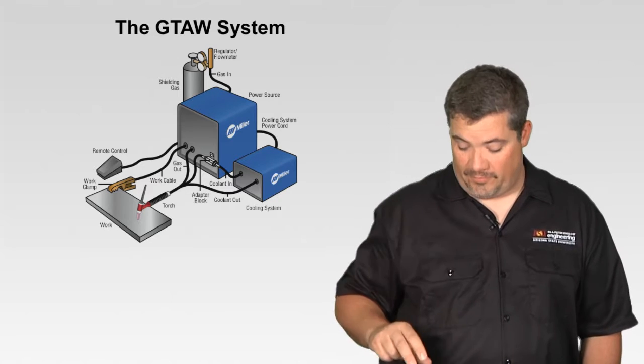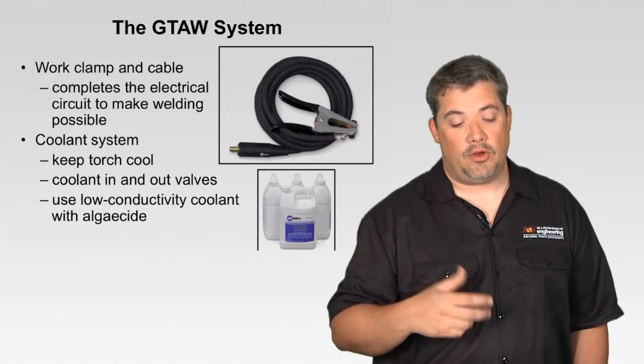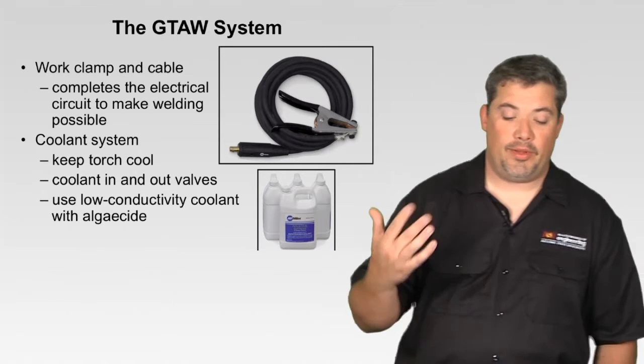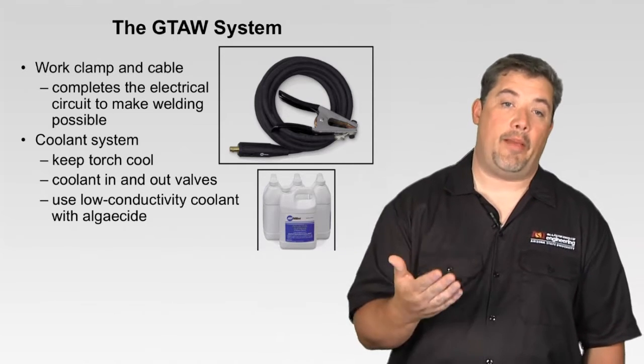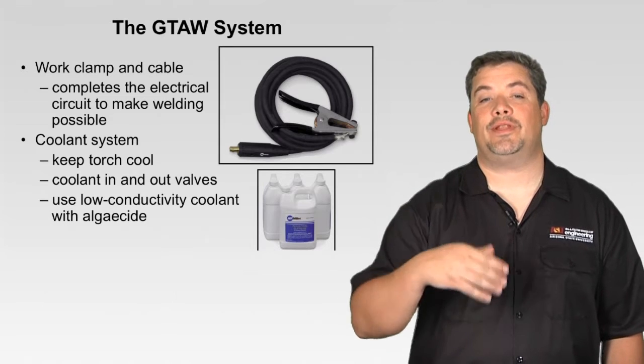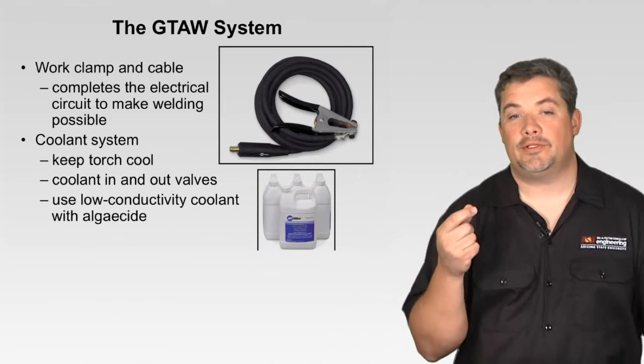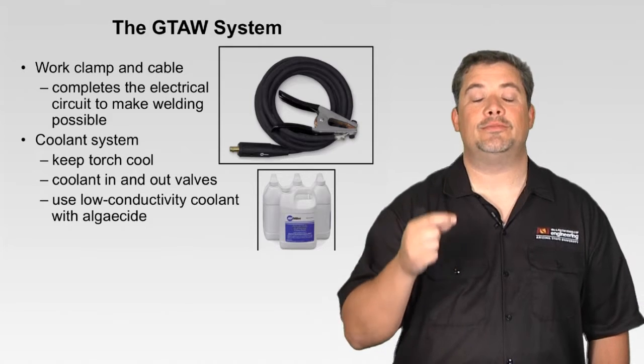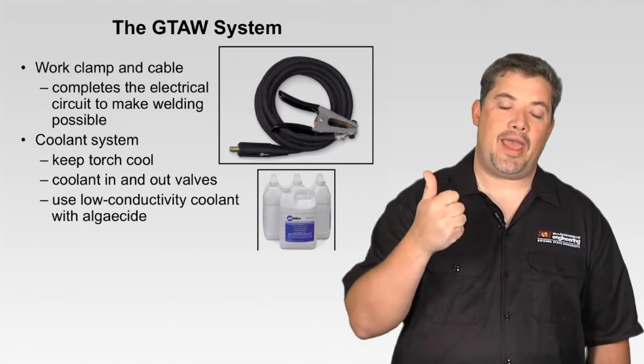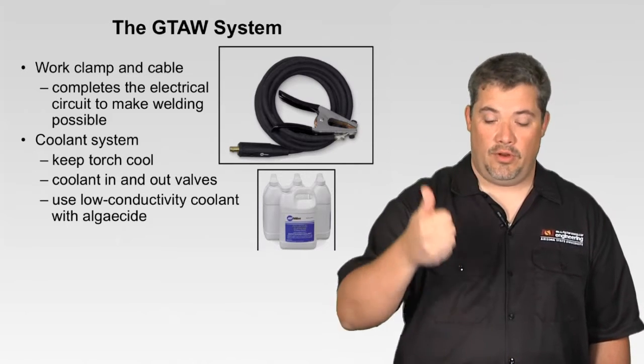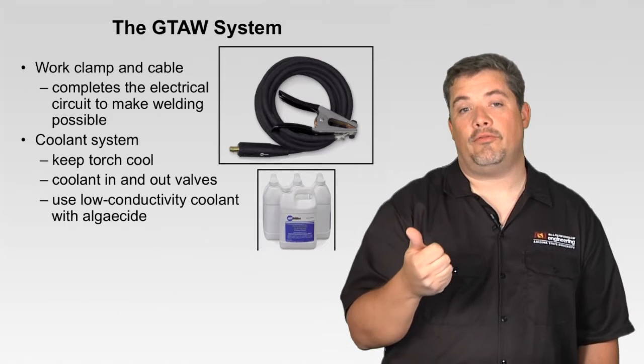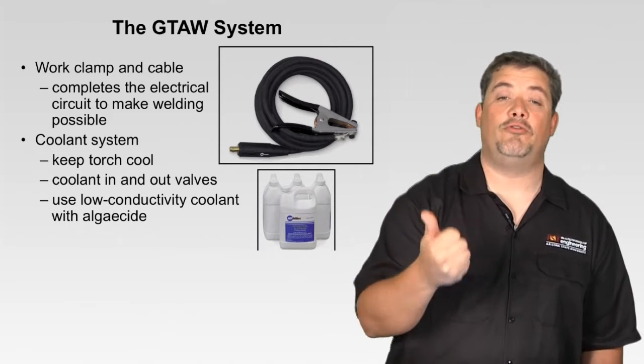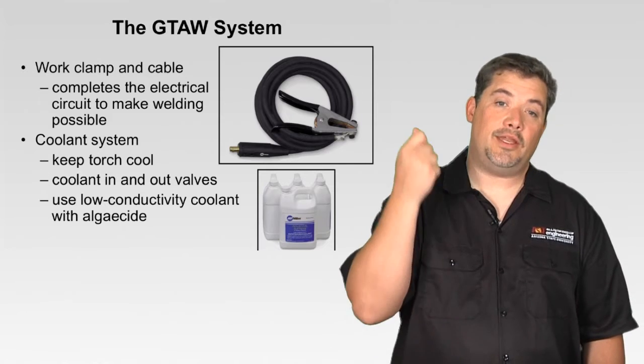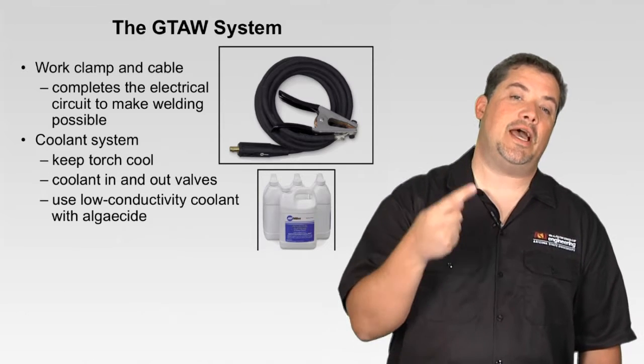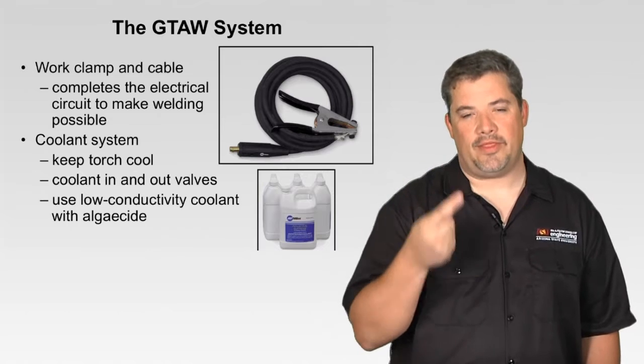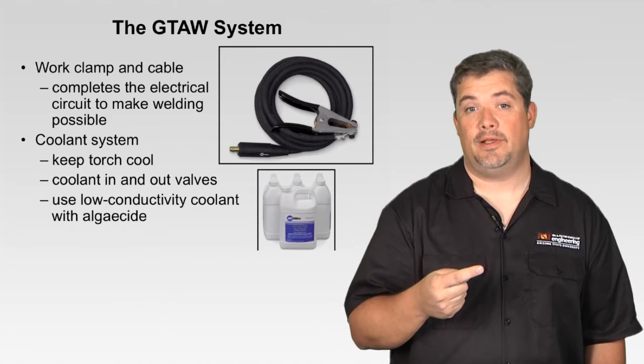So lots more components in a TIG system, so that definitely increases the price of a TIG system. But great welding process. So our work clamp and cable, again, completes that circuit to make the welding possible. Our coolant system keeps that torch cool. But there's some very important things about coolant systems for TIG welding. Number one, you have to use either the low conductivity coolant from the manufacturer. If you use that, it's good for about a year. If you don't use that, then you need to use distilled deionized water. And if you put that in the system, you need to change it every 6 months.